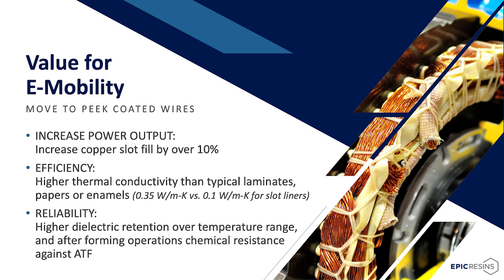Another strong benefit of PEEK is its reliability. PEEK-coated conductors have no pinholes due to the coating process when compared to enameled wires. PEEK can provide a higher coating thickness than enamel wire, providing increased PDIV protection. PEEK-coated wires are resistant to ATFs, especially those that include small percentages of water.